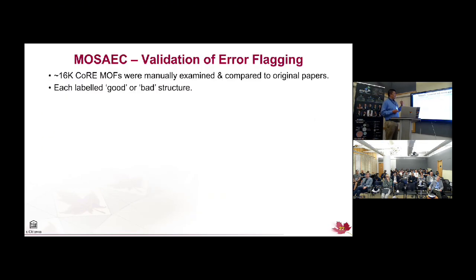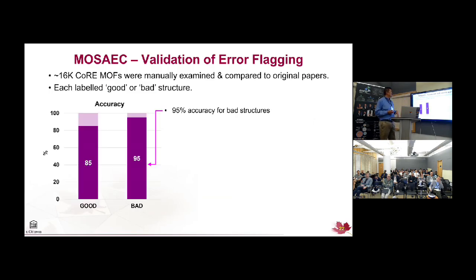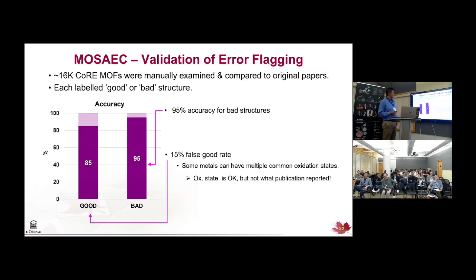Now, how does it do in detecting errors? Well, we manually went through 16,000 of the CoRE MOFs by hand, examined them against the original papers, and labeled them. When MOSAEC says it's bad, it's 95% accurate. So at least for detecting bad structures, we think it's very good. It has a 15% false good rate, but that's because the error might put the metal into a different oxidation state, which is also common and so okay. So then it says it's okay because the oxidation state isn't impossible. But certainly if it says it's bad, it's very likely a bad structure.